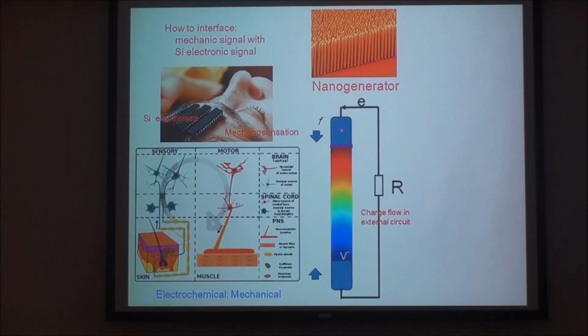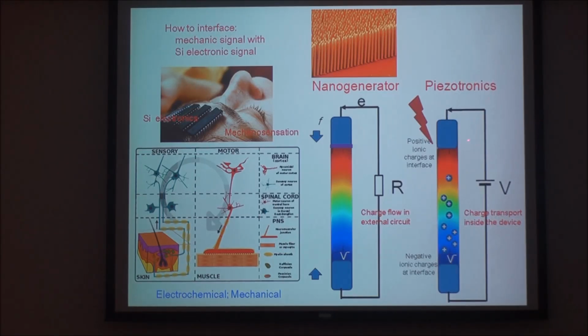I just talked about using piezo potential to drive electron flow in an external load, which is the basic principle of the piezoelectric nanogenerator. This is the way to do it. You do dynamic straining. However, you can do it a different way. If you strain these materials and hold it, the piezo potential is preserved because the ionic charge remains at the end surface. And this charge at the interface can largely tune the transport of the carrier. So when you make the carrier P-type and N-type go through the interface, the piezo potential can affect its transport. So using piezo potential as a gate voltage to change the transport of these carriers inside the circuit is Piezotronics. Okay, so this is the idea.